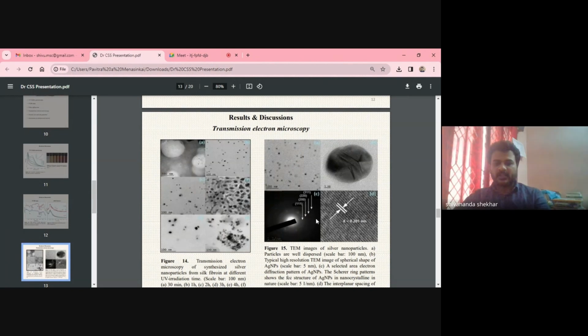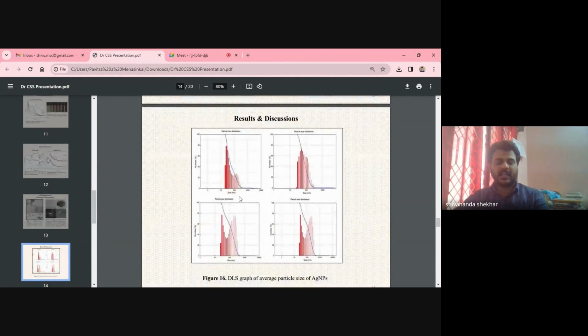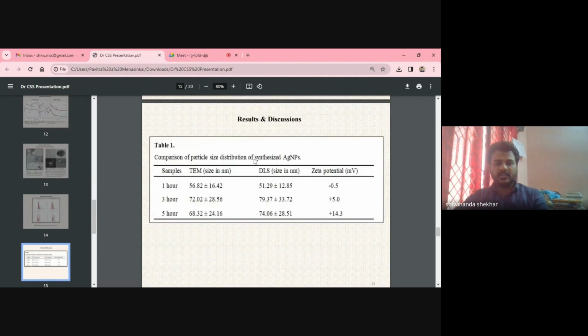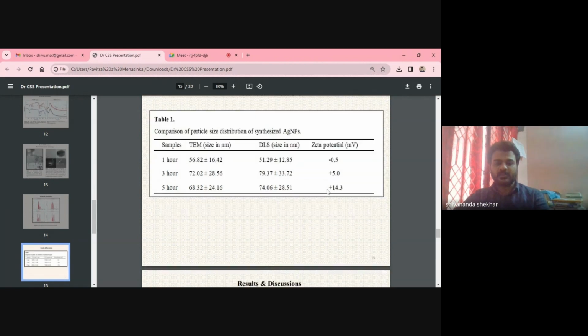Thank you very much. So this is transmission electron microscopy. This is a high resolution image of a single nanoparticle, and this is the interplanar spacing we calculated using image software. This is the SAD diffraction pattern. We also did dynamic light scattering in order to get the stability of the samples, showing how stable the composite solutions are. This is the result and discussion. We calculated the TEM size and the DLS size for the 3-hour irradiation, and this is the zeta potential value.